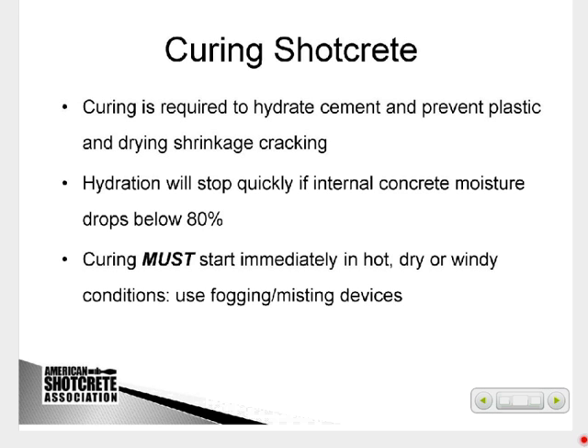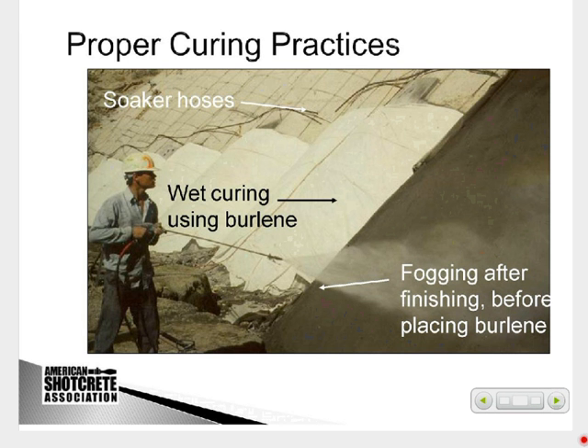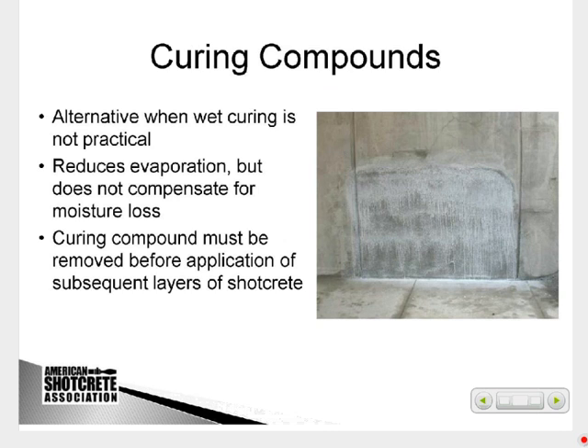And hydration, curing is the same that you have in cast-in-place concrete if you're casting a floor or a cast-in-place wall. Because of the exposure, we often will have fogging nozzles on the site where we can fog the surface, and then we cover it with a blanket, maybe a burlap type material, burlap with plastic on the outside, and then soaker hoses, as are shown here, that actually drip water down below the burlap that's in place. But curing is important for shotcrete as it is for cast-in-place concrete.